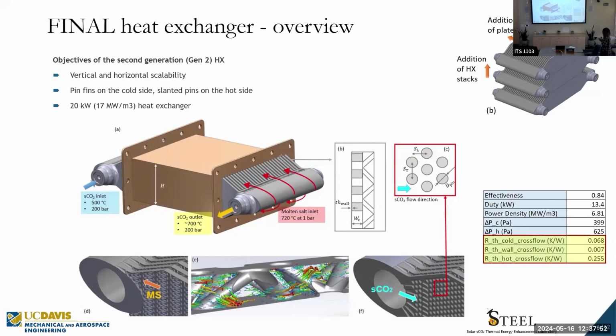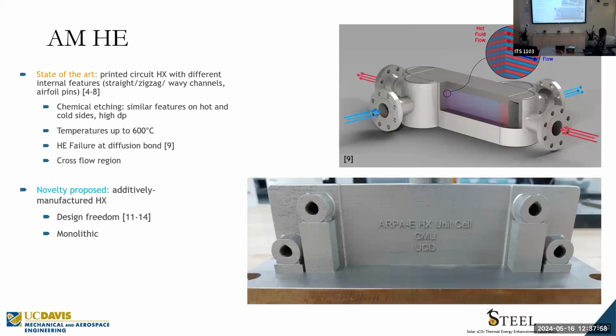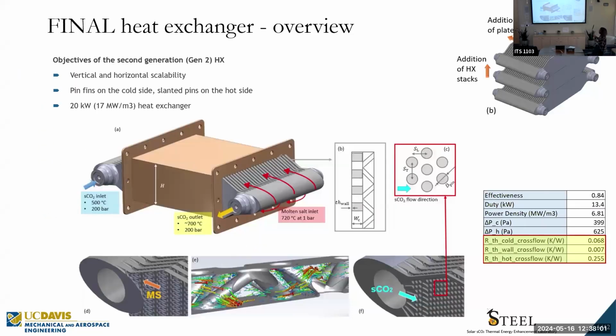And you can also notice that unlike the printed heat exchanger version, the headers, just like Valentina showed with the plastic version, are in the flow, across the flow, so that we minimize the regions that are in cross flow, and we can have the whole heat exchanger being basically in counterflow. And so the schematic here is showing you the cold side where we have pin fins, and the hot side where you can see that the pins look more slanted. And so the idea here was to improve the thermal performance on the hot side.